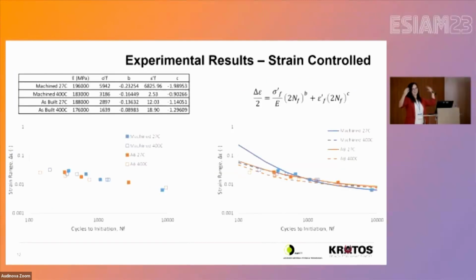So I've thrown a lot at you, but the main points of interest here are that we pulled multiple specimens from multiple locations, not only in our dog bone build, but across our different components. And then we did multiple conditions. So those were as built and a machined smooth surface, and then room temperature, and then 400 degrees. And the interesting thing to note is that we seem to have identified 2 distinct families of response.